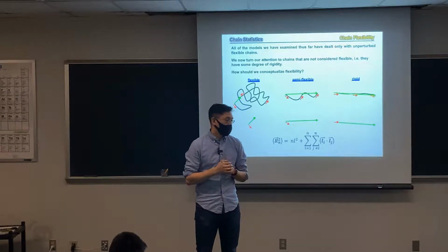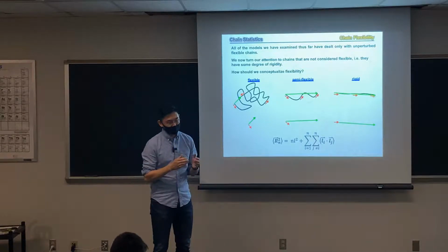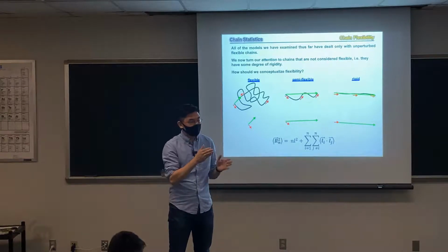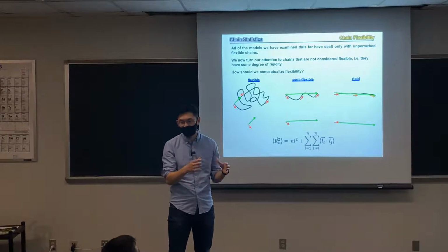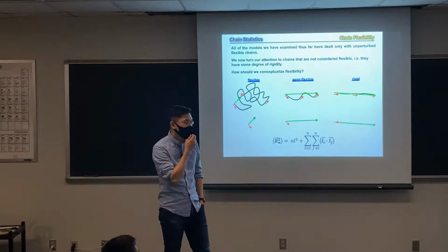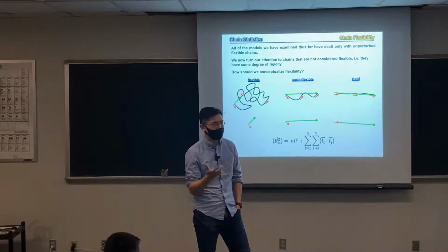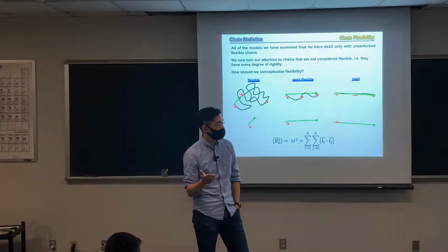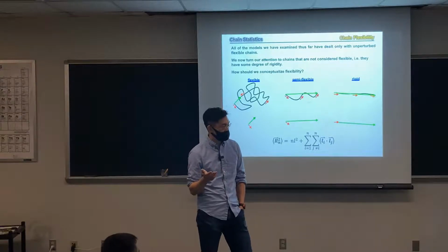In the field I work in, we deal with semiconducting polymers. One of the characteristics is that you have alternating single and double bonds along the polymer backbone. The double bond will make your backbone more rigid, or in some cases like PET, if you have a lot of fused rings, then your rigidity will go up. But we're still talking about LP on the order of just a few nanometers to tens of nanometers, okay? An example would be polythiophene, one of the polymers I deal with.